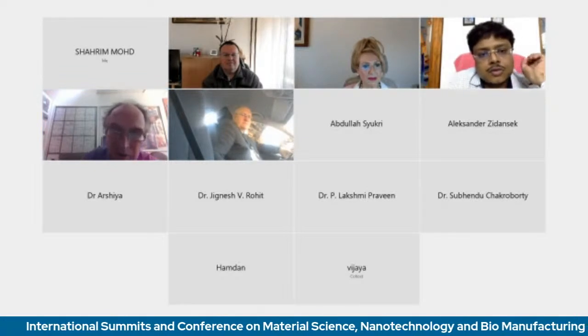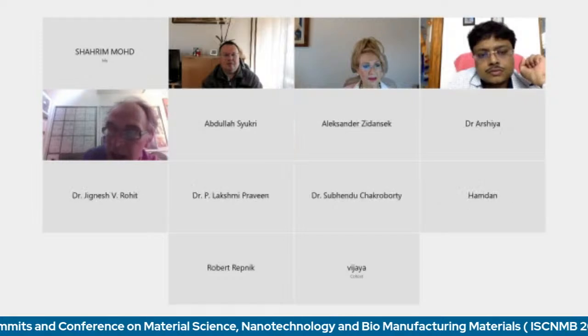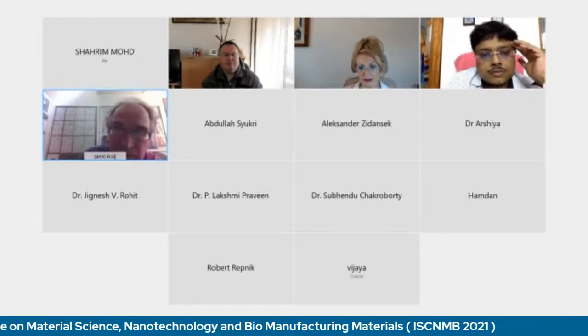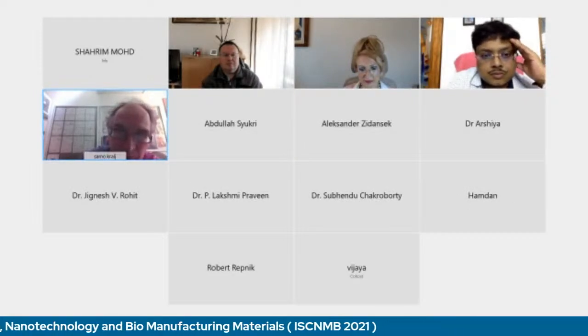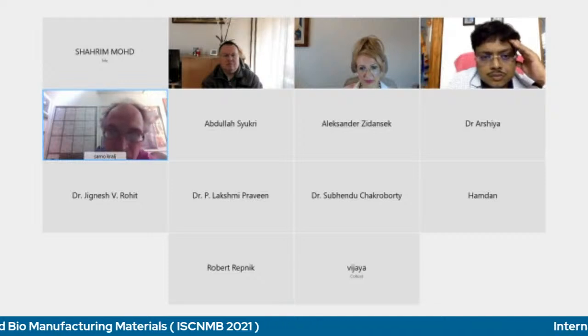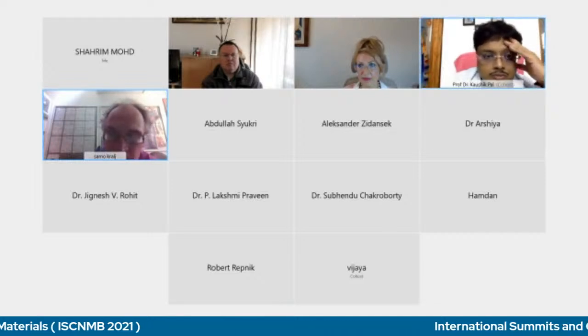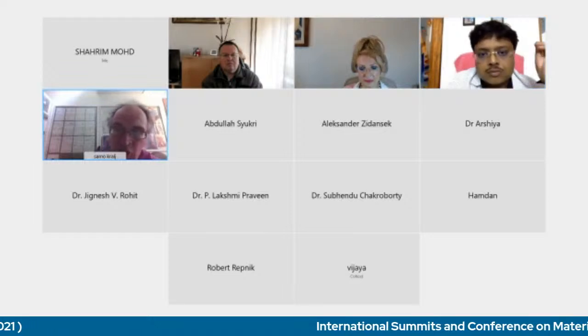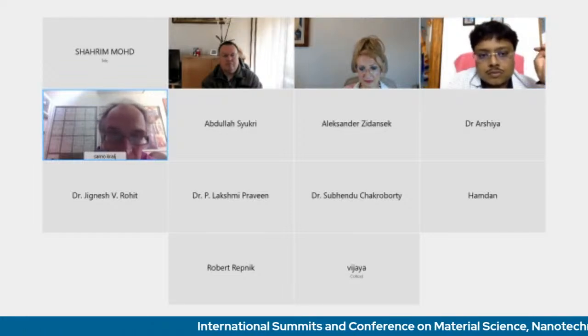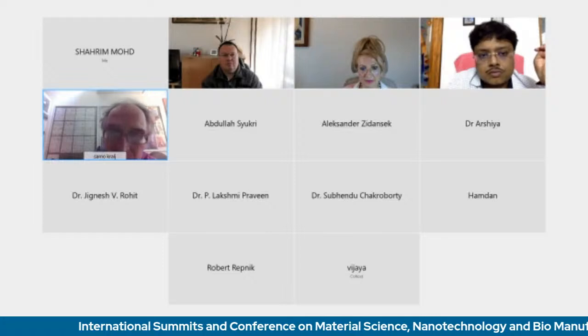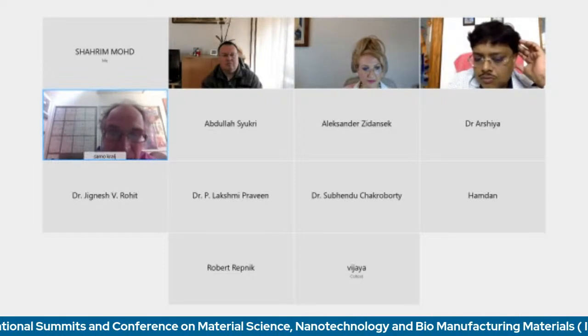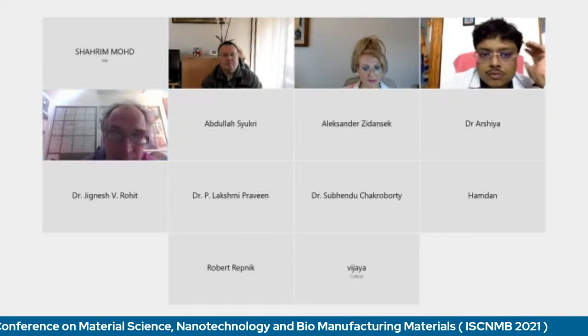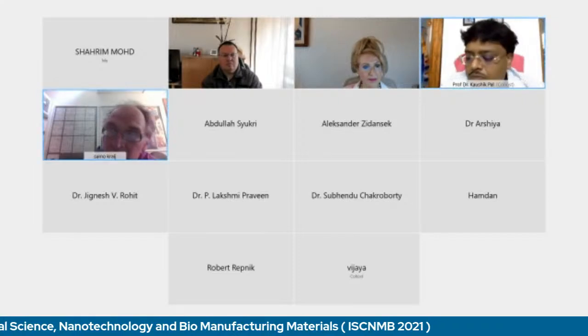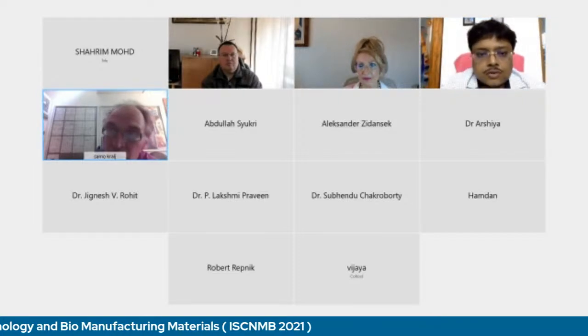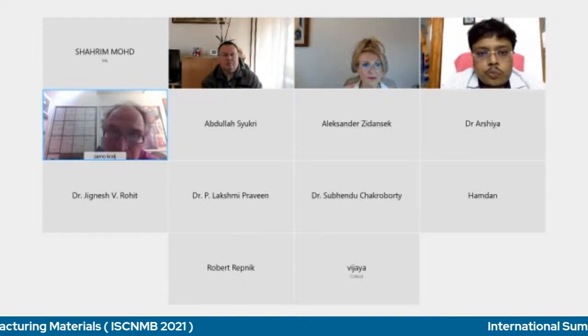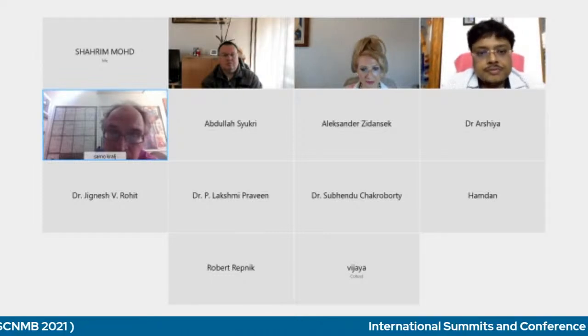But so far, at the moment, we were just using nCB liquid crystals because we have them, but we would like to use also other liquid crystals. So it is important to have large latent heat change. This is the key fact. And so we observed that this response is really great. You have to be close to the phase transition because you have to have the greatest change in orientation and entropy. Nice. Great.